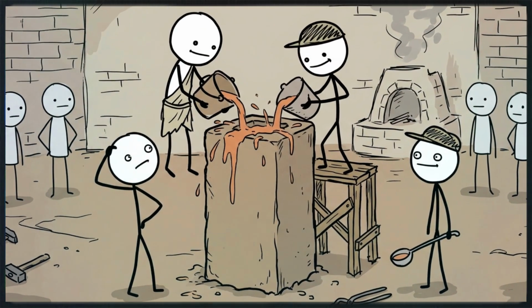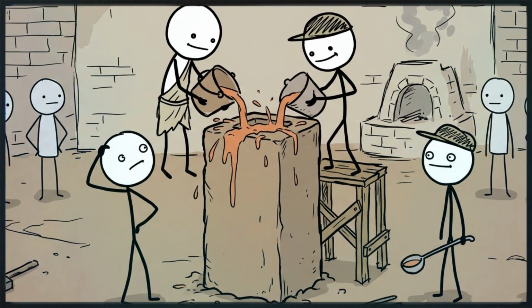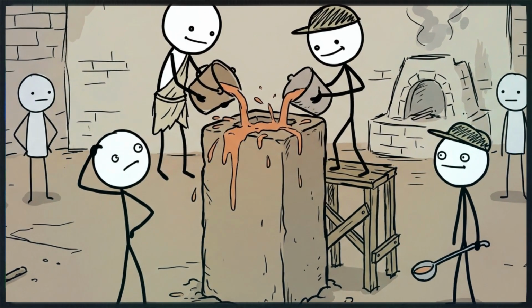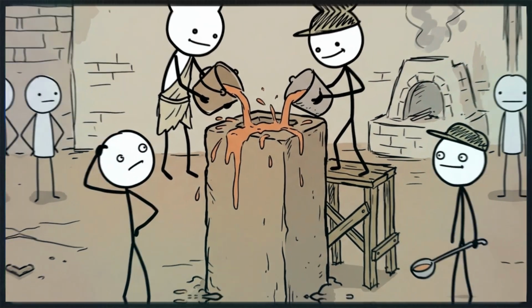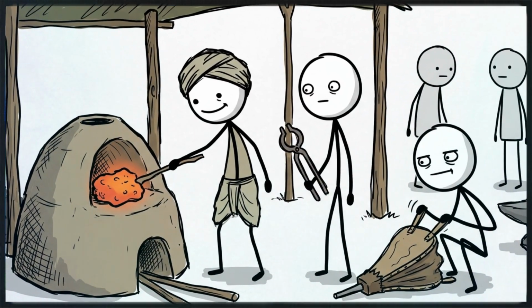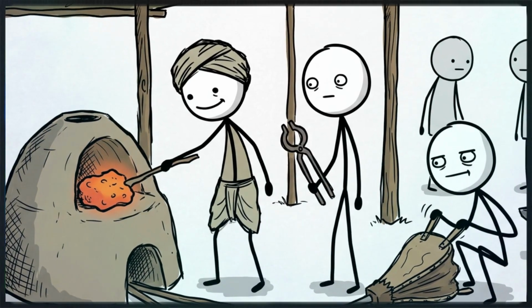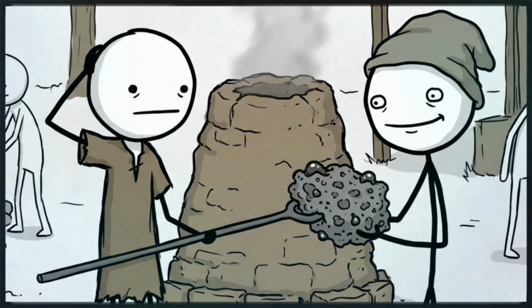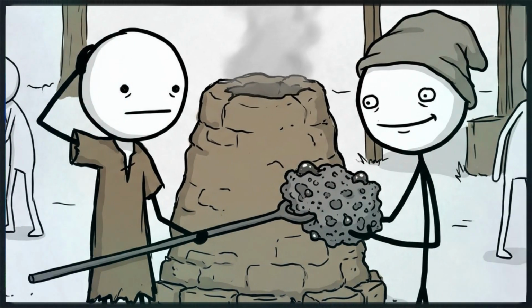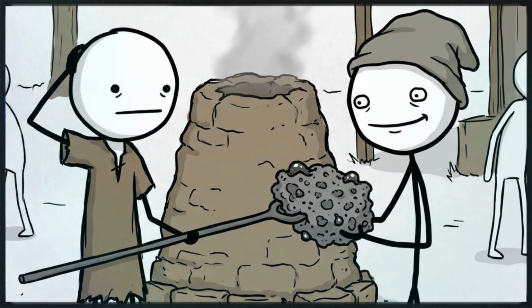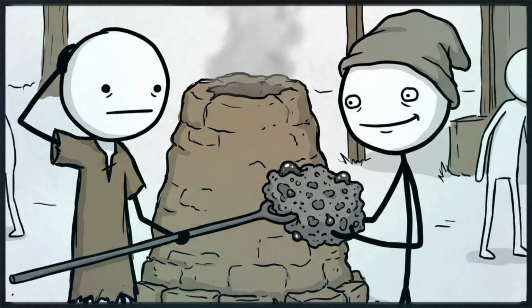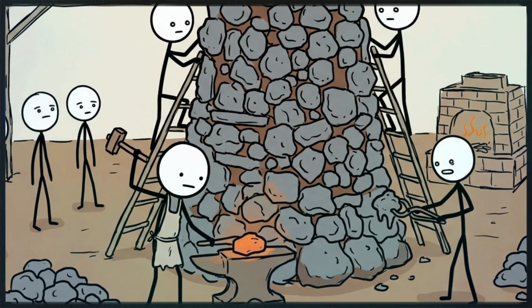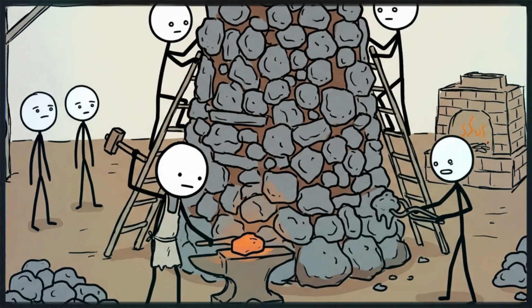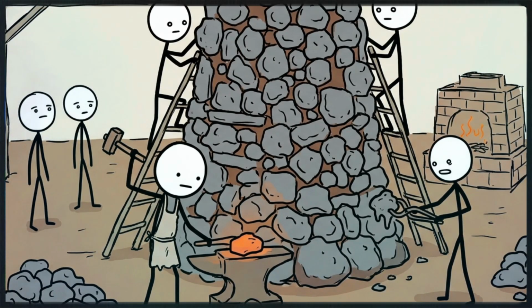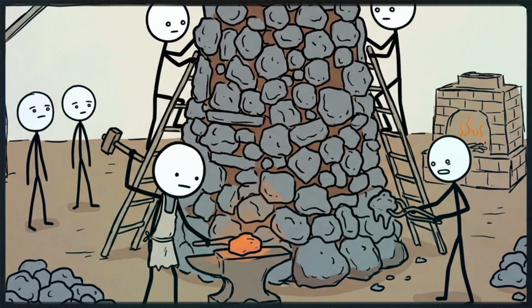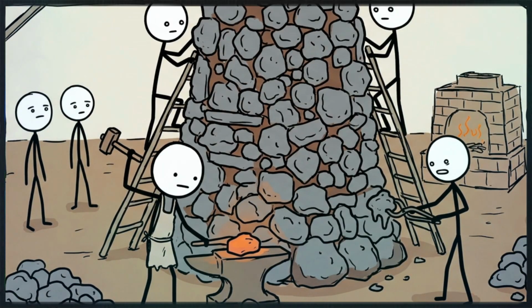The Delhi pillar was not cast by pouring liquid metal into a giant mold, which is how modern foundries operate. Ancient Indian bloomeries could not reach the extreme temperatures required to completely liquefy iron. Instead, they produced sponge iron, porous, solid lumps of iron mixed with glassy slag. To construct a massive 6-ton pillar, an army of master blacksmiths had to meticulously heat and physically hammer hundreds of these distinct iron lumps together.